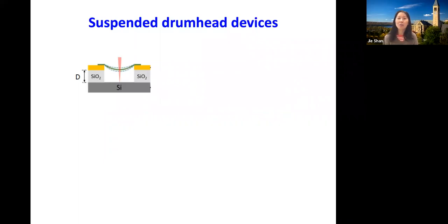And the experiment was done using this drumhead device. So the radius is on the order of 2 to 3 micron because we want to get to relatively high frequency. And this is the membrane, 2D materials. We put on top of the drumhead, the trenches with electrodes, and the silicon serves as backgate. So you can apply a large gate voltage here just to pull down the membrane. So this is the way to apply continuous strain on the magnetic field and at low temperature.